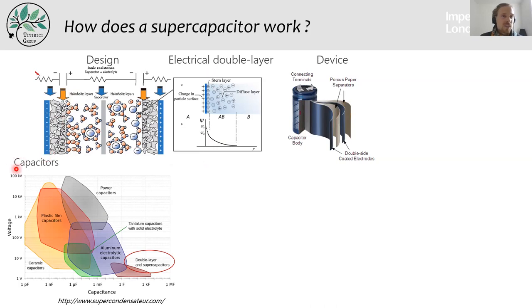And compared to standard dielectric capacitors that you've probably heard about that are used in electronics, these dielectric capacitors have, instead of having an electrolyte here, a dielectric material, which allows them to be used at really high voltage. But unfortunately, because the charges available are only the electrons within the electrode, they don't have a lot of capacitance. So that's why they are in this field here on the graph. Whereas supercapacitors have electrolyte ions, which add on to the charges available to create the capacitance. So they have really high capacitance, but unfortunately we can't use them at really high voltage because otherwise we would destroy the electrolyte. And that's why they are on this end of the graph.